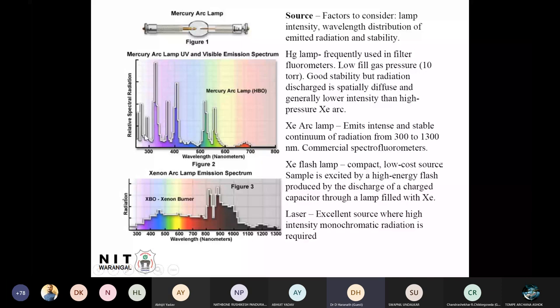Suppose your material absorbs in this region. If you measure the absorption of the material you have developed, and the absorption lies around 495 nanometers, and you put it under this mercury lamp, which does not have that wavelength, your material will not glow. Then you feel that your instrument is not working or your sample is not good. Whereas this xenon vapor lamp has a very broad spectrum and you don't see any wavelength missing. Of course, there is a drop here and it comes back again, but it is almost broad.